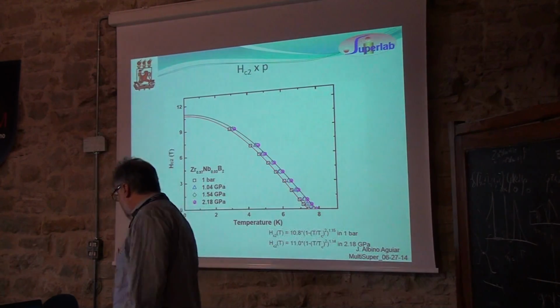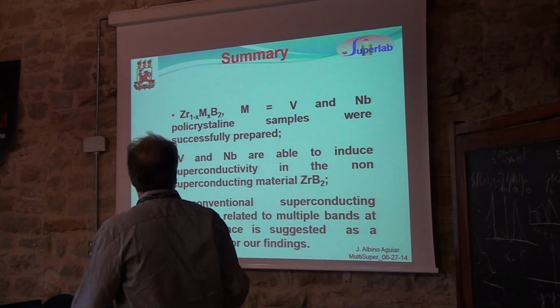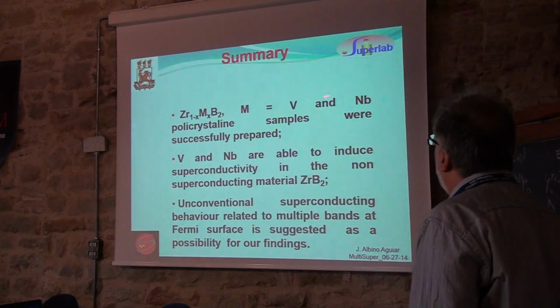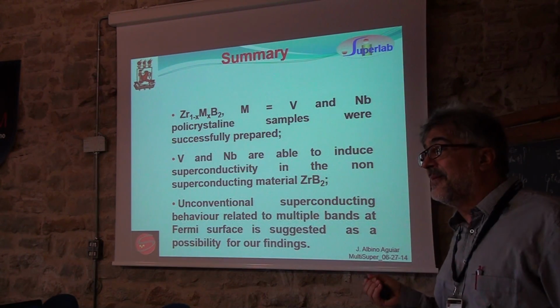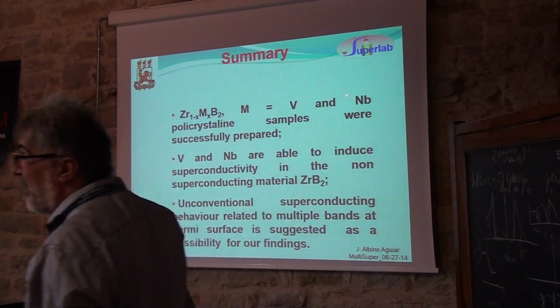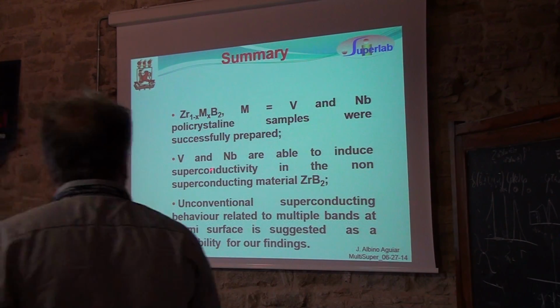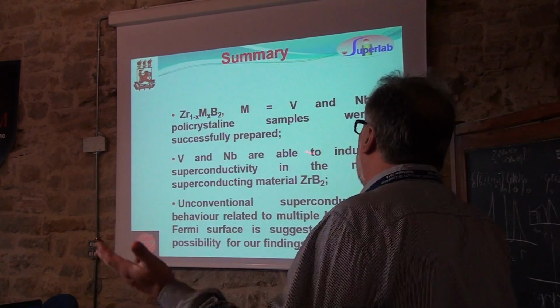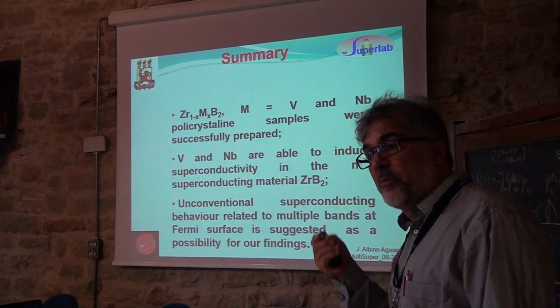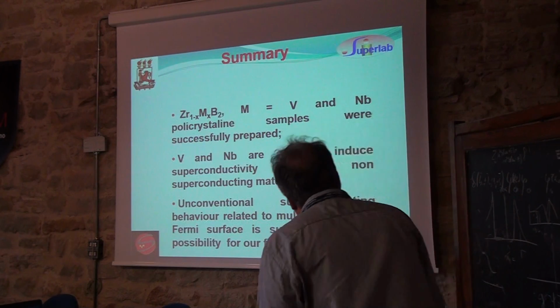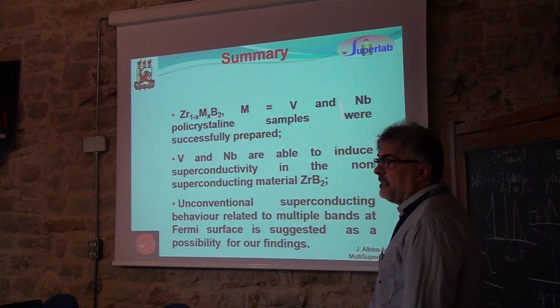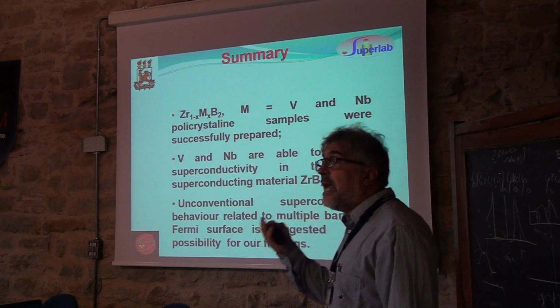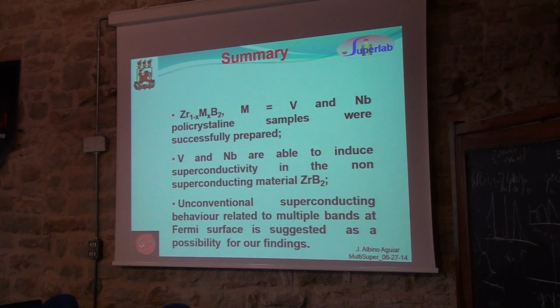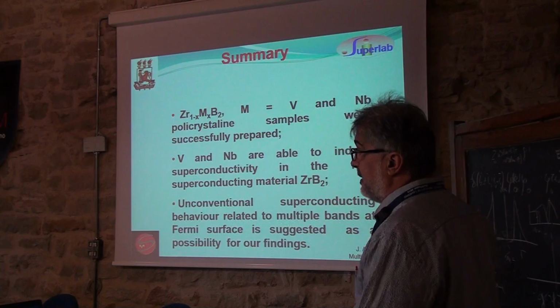And then I come to my conclusion or summary. We succeeded to prepare polycrystalline samples. You see that I don't speak here about the single crystal. What we proved is that vanadium and niobium are indeed able to induce superconductivity in this non-superconducting material. And we have evidence that it is unconventional. If it's true, as we suggest, it's not proved yet.